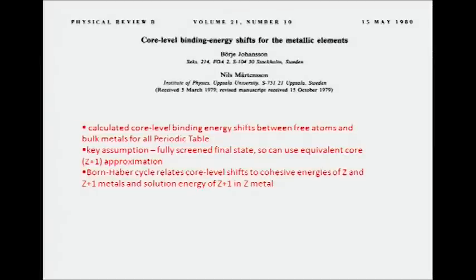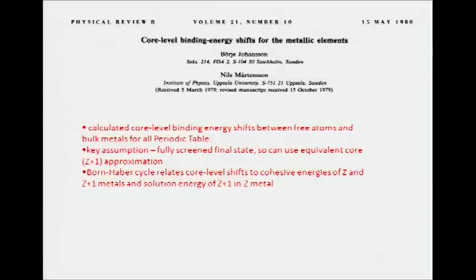And the key assumption is basically that for the final state, that is the core ionized state, you assume you've got complete screening in the metal, and so you can represent what happens in terms of the valence electrons by this Z+1 approximation: removing a screening electron near the core, and hence increasing the nuclear charge effectively to the outer electrons, is equivalent to just putting an extra proton in the core. And then by a rather neat trick using this Born-Haber cycle, you can relate these core level shifts, the shift between the atom in the free atom and the atom in the metal, to just the cohesive energy of these two elements, the Z and the Z plus 1, and the solution energy of the Z plus 1 in the Z.